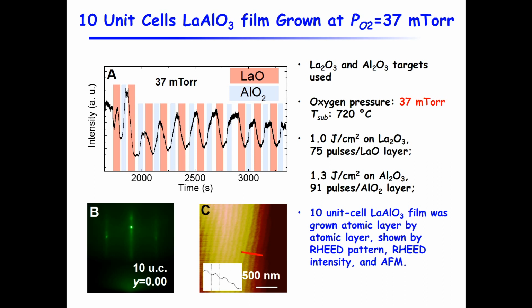And this is starting from the titanium oxide terminated substrate. The very first lanthanum oxide layer gave us this down, up, and down kind of feature, which I think reflects the fact that we are transitioning from the substrate to these films. We don't know how to explain all these features. But once we have this aluminum oxide layer, everything starts to grow very regularly.